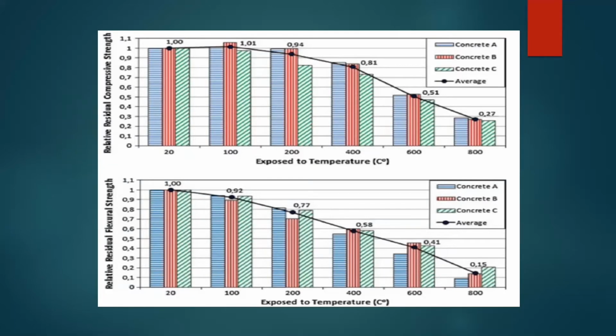This change of property of concrete material under high temperature is mainly due to the evaporation of water in concrete. Also the property changing of aggregate and cement materials. The bond strength between cement and aggregates also reduces under high temperature. However, concrete can reach maximum 80-90 degrees even when atmospheric temperature reaches 45 degrees. So it is almost impossible for concrete to reach these high temperatures. The concrete can keep its compressive strength under high temperatures, but high temperatures can influence the flexure strength dramatically as shown in the figure.